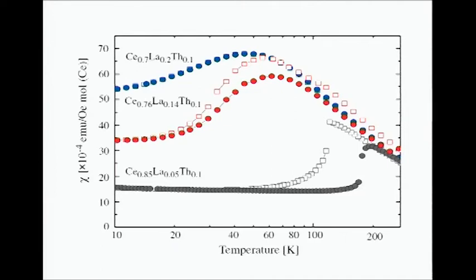The phase boundary for the tricritical point looks like this. This is magnetization versus temperature with increasing lanthanum, and you can see that the hysteresis goes away. I know it's a bit of a nebulous argument without microscopy data, but it is the best phase diagram we can put together right now.